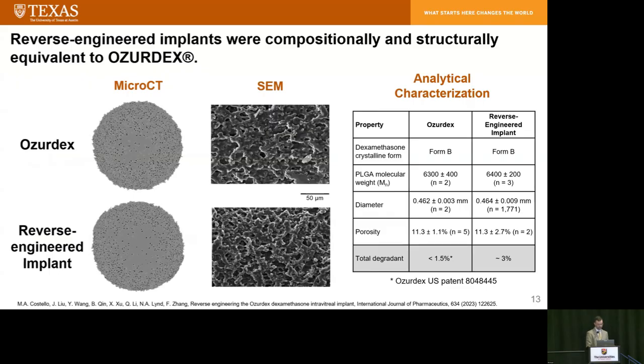Here's how our finished implants stacked up next to Ozurdex. So for all of the critical quality attributes that we identified, everything looked great in comparison. So we used micro CT to analyze the porosity. With that technique, we can measure the pore size distribution, as well as the radial distribution of pores. You can see that there are more pores toward the outer region, there's fewer pores in the center of the implant.